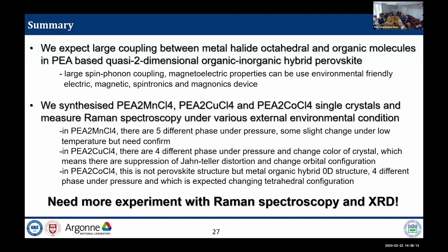In the PEA2 manganese tetrachloride, there are five different phases under pressure and some slight change under low temperature but need to confirm. And in the PEA2 copper tetrachloride, there are four different phases under pressure and a changing color of the crystal, which means there is suppression of Jahn-Teller distortion and a change in orbital configuration. And the PEA2 cobalt tetrachloride is not a perovskite structure, but a metal organic hybrid, zero dimensional structure. So there are four different phases under pressure, which is expected to change the tetrahedral configuration.